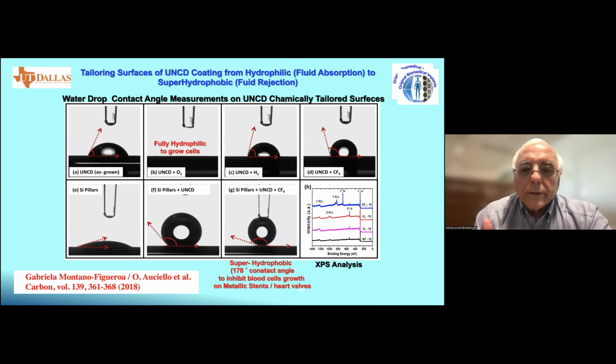So here we see that with oxygen plasma, we can make the UNCD surface totally hydrophilic for the growth of the cells, but with 5-10 minutes of carbon tetrafluoride plasma, we have demonstrated the highest superhydrophobic surface, with a contact angle of 178 degrees. Nothing sticks to the surface of the superhydrophobic UNCD.